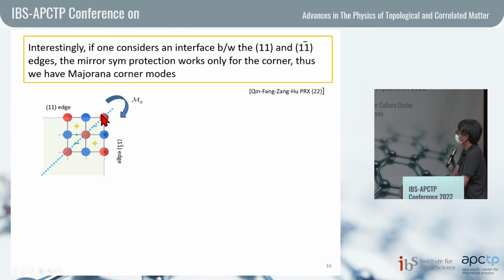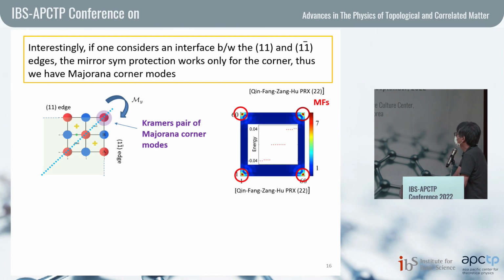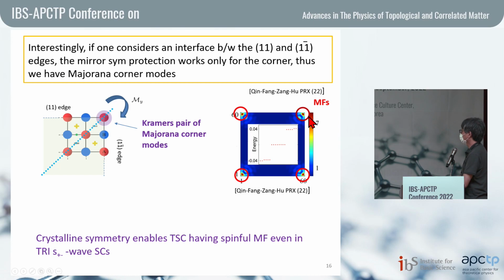However, as you can see, this corner is invariant under the mirror reflection symmetry. So we can obtain a mode protected by the mirror reflection symmetry. And actually, we can obtain a Kramers pair of Majorana corner modes because we have time reversal symmetry in the system. Here I show the numerical calculation done by them, and they show that there exist 8 zero modes in this configuration, which means that there exists a Kramers pair of Majorana zero modes at each corner. Anyway, the crystal symmetry enables the topological superconductor to have a spinful Majorana fermion even in time reversal invariant S plus minus wave superconductors.